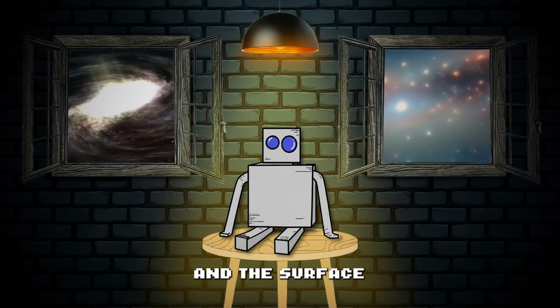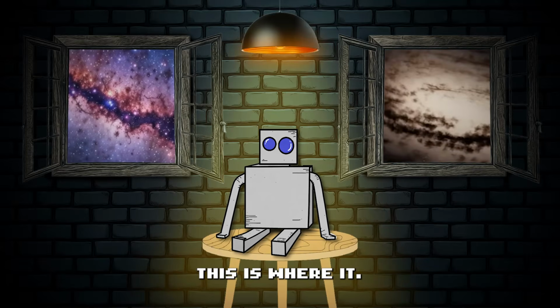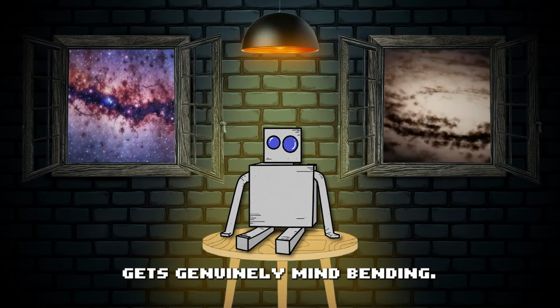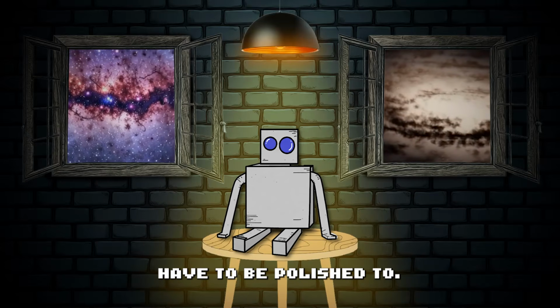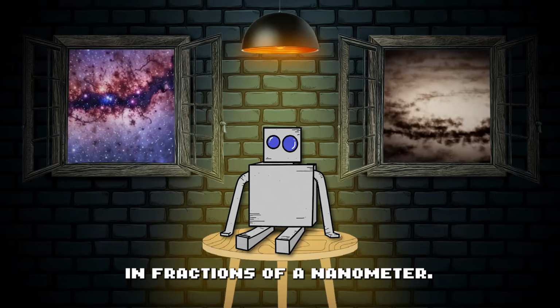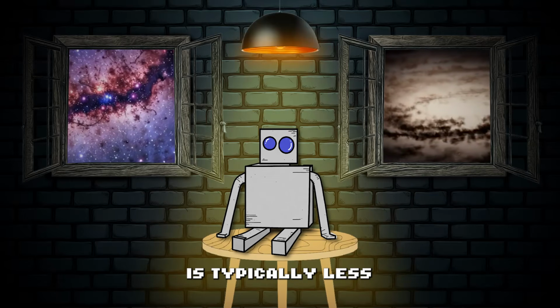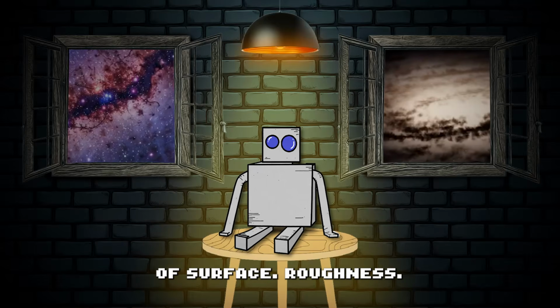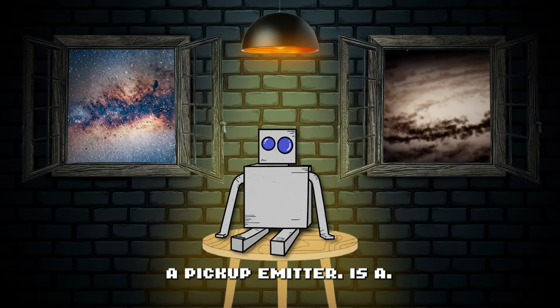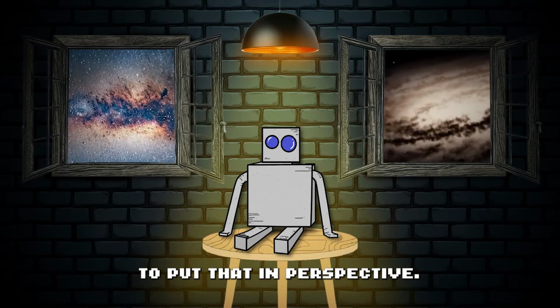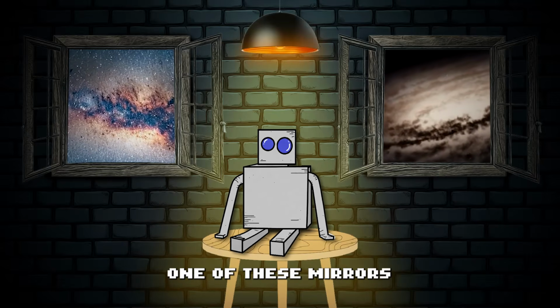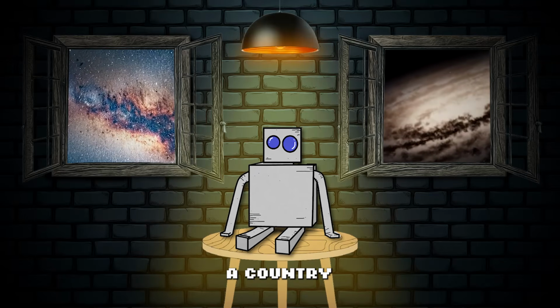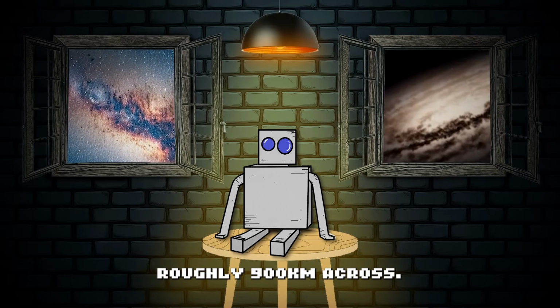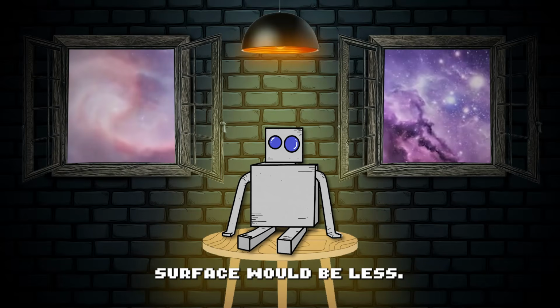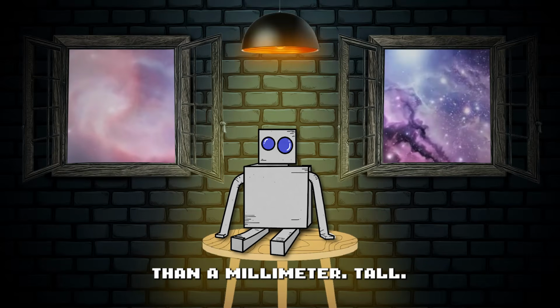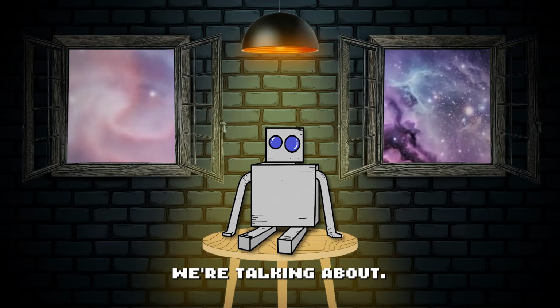And the surface quality of these mirrors? This is where it gets genuinely mind-bending. The mirrors have to be polished to a smoothness measured in fractions of a nanometer. The specification is typically less than 50 picometers of surface roughness. A picometer is a trillionth of a meter. To put that in perspective, if you scaled one of these mirrors up to the size of Germany, a country roughly 900 kilometers across, the largest bump on its surface would be less than a millimeter tall. That's the level of perfection we're talking about.